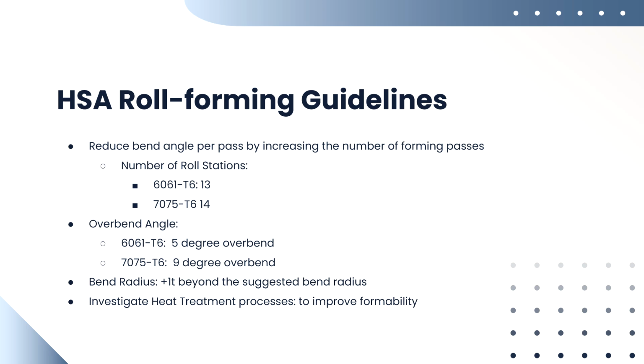To achieve a 90-degree angle, it is recommended to overbend 6061 T6 by approximately 5 degrees, and 7075 T6 by approximately 9 degrees. For bend radii, we suggest using a radius at least one material thickness larger than the recommended bend radius. Finally, heat treatment methods should be investigated to improve the formability of high-strength aluminum alloys.